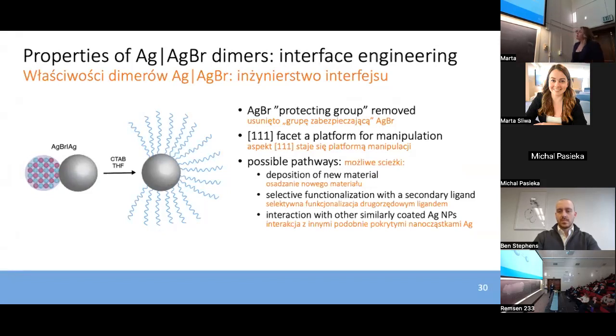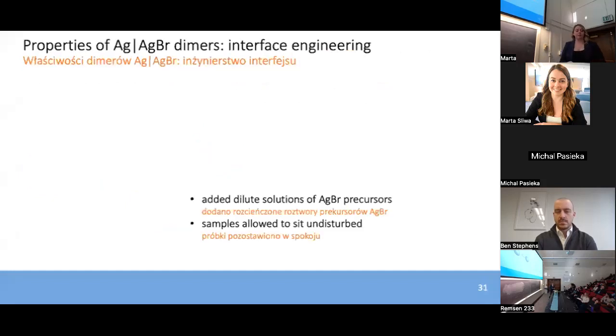So there are a number of different pathways that we saw we can potentially manipulate the dielectric environment at this facet. We could potentially deposit a new material or grow a new material on the 111 facet, functionalize it or add different ligands to that area to create a dielectric environment that's different here that way, and also potentially coax interactions with other similarly coated silver nanoparticles to get them to make multi-component structures.